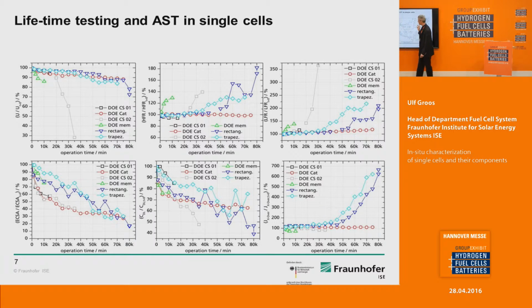You see different graphs which show the degradation behavior regarding certain parameters. So in this graph you see the degradation of the voltage. Here you see degradation regarding the high frequency resistance. This is the low frequency resistance. Here you have the electrochemical surface area, which degrades over time, the double layer capacity, and the crossover current.